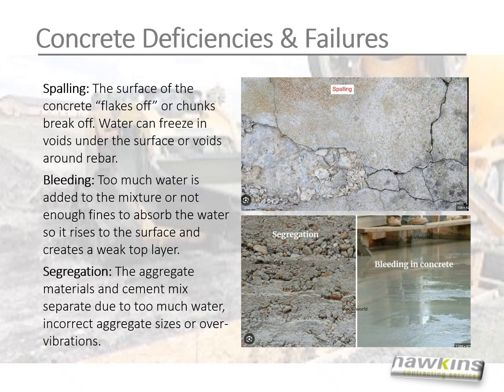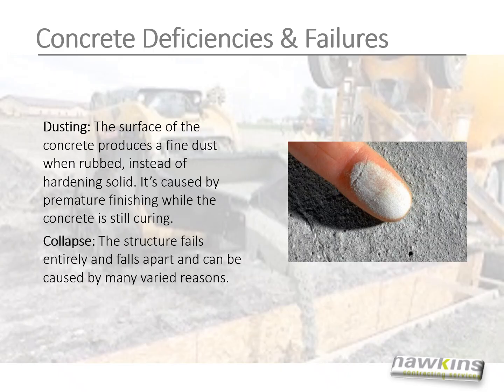Spalling. The surface of the concrete flakes off or chunks break off. Water can freeze in voids under the surface or voids around rebar. Bleeding. Too much water is added to the mixture or not enough fines to absorb the water, so it rises to the surface and creates a weak top layer. Segregation. The aggregate materials and cement mix separate due to too much water, incorrect aggregate sizes, or over vibration.